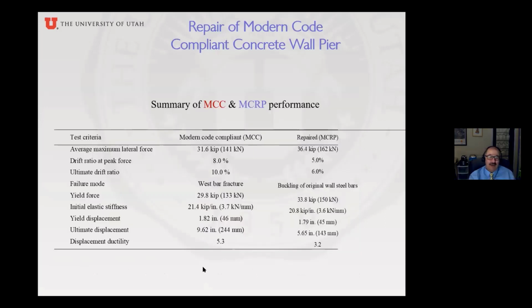So as a comparison, what was the modern code compliant? It was 31 kips, say 32. The repair was 36. The drift at the peak was 8. Here we got to 5. The ultimate was 10. Here we got to 6. The failure mode in the original was west bar fracture. Here we saw a little buckling of the wall bars above the plastic hinge.